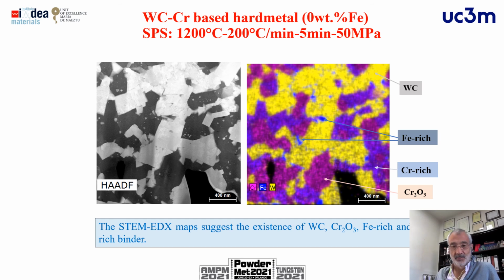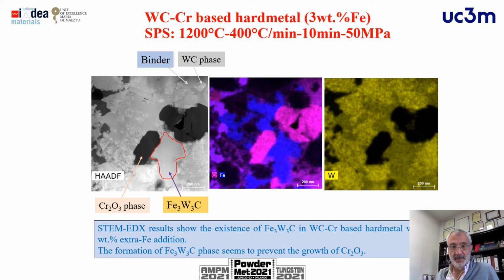And you can see here that we have the binder. This is the binder phase, the black one, and this is the tungsten carbide, the white one. Analyzing the compositions by STEM EDX, developing STEM EDX maps, we can see some chromium oxides also in between the tungsten carbide and the chromium iron binder. So if we introduce iron, we have the presence there not only of the chromium oxide, but also the formation of this iron tungsten carbide that in some way is better than the eta phase, because this carbide in some way also prevents the growing of the chromium oxide and allows us to reach good levels of toughness.